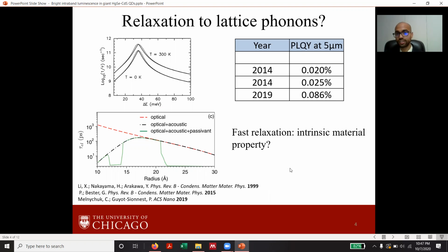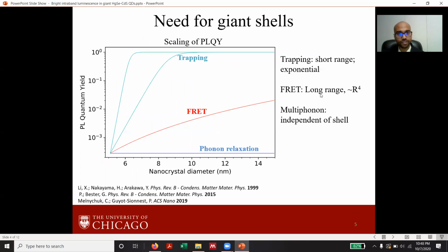If this is true, this is very bad news for us because the relaxation is limited by an intrinsic property of the material, and there's nothing we can do about it. And this is in line with reported efforts for trying to get bright mid-infrared luminescence in quantum dots. Though efforts have been put over the years, there is only a marginal increase in the quantum yield, and it is still less than 0.1%.